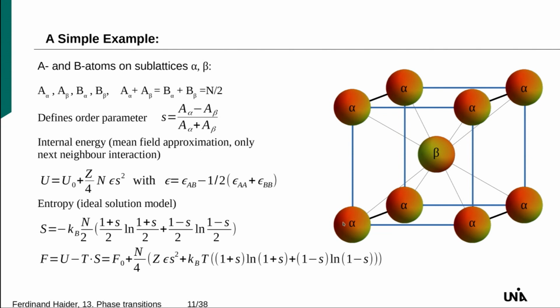It means to count the number of AB pairs, for example. I can start with an A atom here, and then I have to know the probability that there is a B atom on the neighboring side. The approximation done here is that this probability is just the occupation of these sites with B atoms, so this B beta. If you make this assumption, you end up with this simple expression for the internal energy.